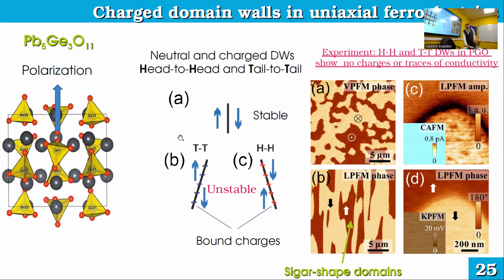If you remember all this divergence P stuff about bound charge, then in these uniaxial ferroelectrics, only two types of domain walls are possible: head-to-head, where vectors meet, and tail-to-tail, where vectors diverge. It's natural to expect that these domain walls will be charged. And that's actually the case. For example, lithium niobate, a very famous uniaxial ferroelectric, has a very strong charge on the walls inside the material.